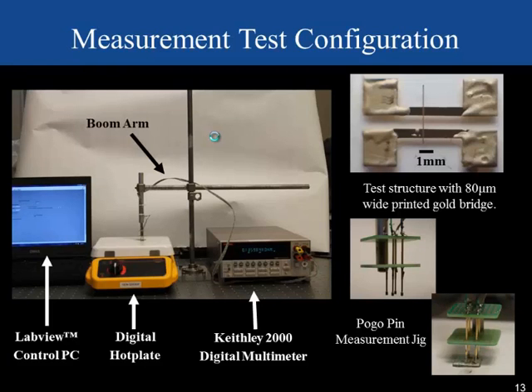Measurements were performed, and here's a resulting structure from our work, and you can see the printed gold line here. This test setup was then used for our measurements, and a custom spring-loaded pogo pin jig was used to connect the device to the instruments. The pogo pins were used to allow secure probing as well as to allow for thermal expansion of the test setup. Additionally, a hot plate provided temperature control, a digital multimeter provided measurements, and a LabVIEW control PC provided data acquisition.